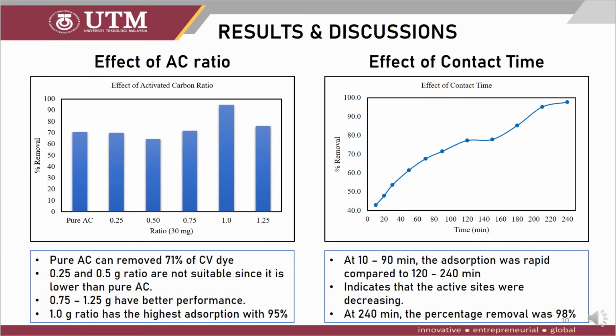So this is the results and discussion for the different parameters involved in this experiment. The first parameter is the effect of activated carbon ratio. As you can see here, pure activated carbon without silver nanoparticles can only remove about 71% of crystal violet dye. However, the 0.25 and 0.5 gram ratios of activated carbon are not suitable since they are lower than pure AC in removing this crystal violet dye. However, the 0.75 to 1.25 gram ratios have better performance, especially the 1 gram ratio because it has the highest adsorption capacity with 95% removal of crystal violet dye.